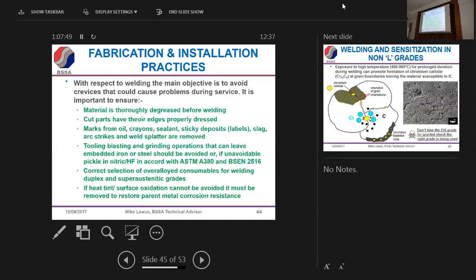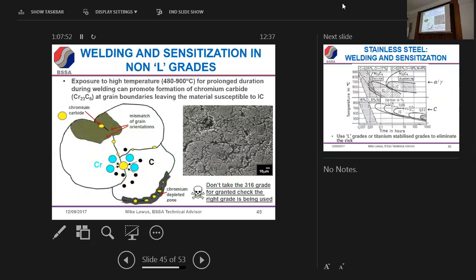I'm going to skip the rest, they're all learning points, but they're very easy for you to read. Just one thing I was going to come back to, something I started with right at the beginning: the difference between L and non-L grades. If you've got 316 and it's the high carbon grade, not the L grade, and you're welding it, you've got to raise the temperature, whatever welding technique you use, very likely to between about 500 and 600.